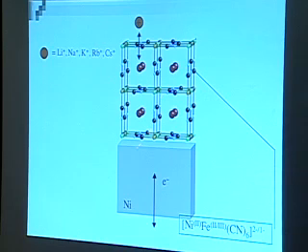And you can make about 1,000 angstroms at the most of nickel ferricyanide, and at that point you generate no more nickel ions. That is, it shuts down and you have a stable surface with a nickel that no longer decomposes, which is actually what I was trying to do, and a nickel ferricyanide lattice that I can put electrons into and out of via these irons here. Now when I do that, I obviously